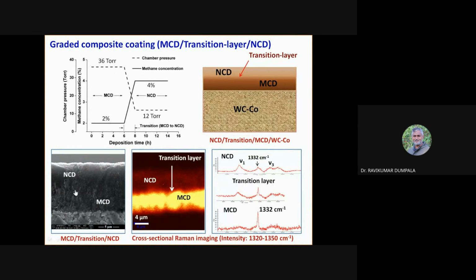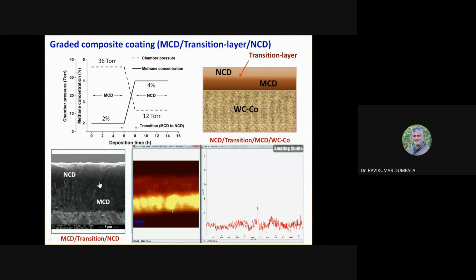To publish that, the reviewer asked how to distinguish them. Then we did some Raman spectroscopy study, because you need a technique to distinguish nanocrystalline diamond and microcrystalline diamond. In the previous case, SEM was fine. In this case, we are able to see two different layers with Raman spectroscopy. I captured some video also, where you can see that when changing the zone, the spectrum is changing. A sharp peak means high crystallinity. Where the sharp peak disappears, it is nanocrystalline in nature. That's what it explains.